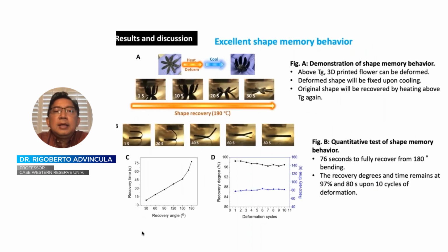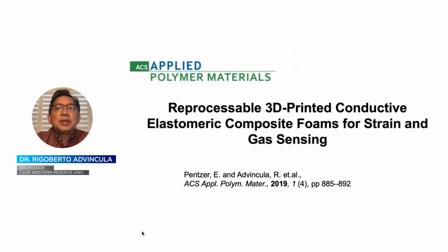Now, the shape memory effect as shown here. So when we initially form the star or starfish, if you want to look at it that way, we can heat the form and then cool the object. And we can cycle this shape memory or change, unfortunately, only in one direction. We are working on a cyclical mechanism and material. So for example, this shape change occurs in a matter of 30 seconds. So when we heat, which deforms the material, cool it, it retains the shape, and then after 30 seconds, it starts flattening. And as you can see here, folding, or the ability to change the fold and the amount of time it takes to fold, qualifies it as a combination of the 3D printing design as well as the composition of the material we have.